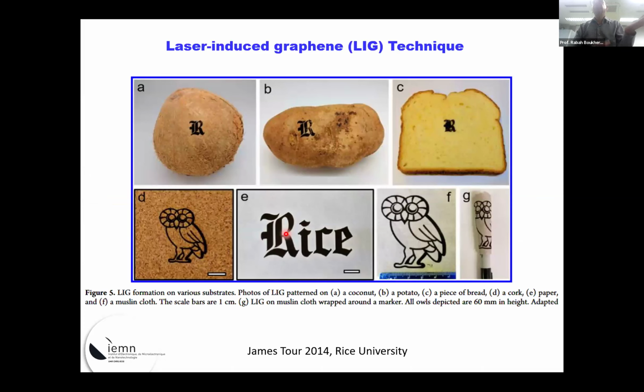It was graphene oxide, to transform graphene oxide to reduced graphene oxide with a laser. And in turn, indeed, there is a formation of graphene. That was developed by the group of James Tour at Rice University. So then they applied this for almost everything.